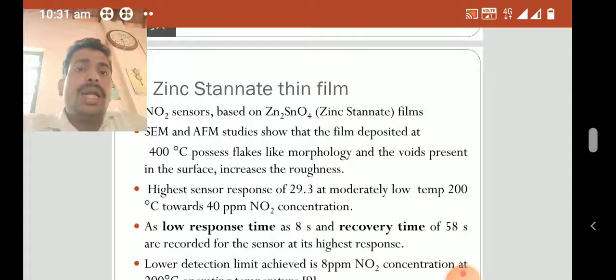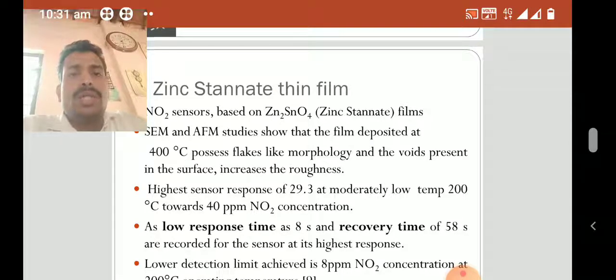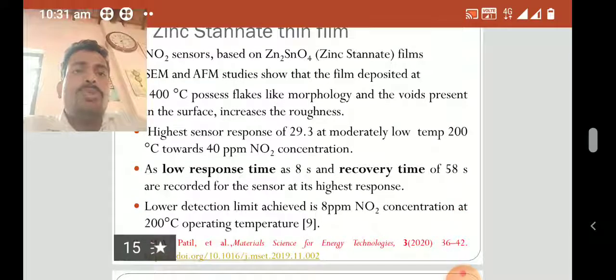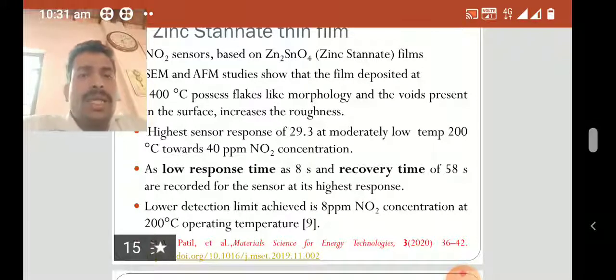A higher sensor response of 29.3 at a moderately low temperature of 200 degrees Celsius towards 40 ppm nitrogen dioxide concentration was observed. A response time as low as 8 seconds and recovery time of 58 seconds were recorded for the sensor at its highest response. The lower detection limit achieved is 8 ppm nitrogen dioxide concentration at 200 degrees Celsius operating temperature.